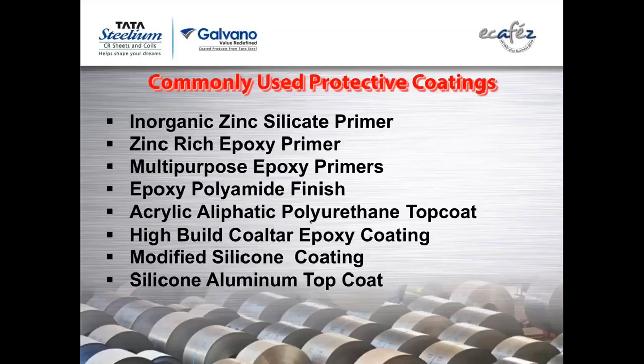A very effective and very good finish. Then acrylic aliphatic polyurethane top coat. I have specifically written acrylic aliphatic because in polyurethane the hardener is isocyanate. Now it can react with the hydroxyl group available in any polymer and form a chain. So even alkyd with that can also become a polyurethane paint, but that will not give you the right outdoor resistance. So better write that acrylic.